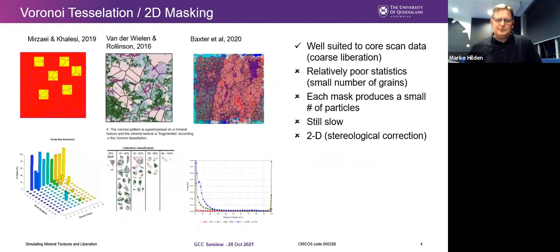Another popular modeling method is to use 2D images of the intact texture and to overlay a tessellation or fragmentation mask, which defines the particles. So simple shapes like circles or squares have been used, but a lot of the recent work uses Voronoi tessellations. An advantage of this approach is it has the potential to be extended to non-random breakage as well. Also, the method is well suited to core scan data and studying coarse liberation. But again, each tessellation makes only a relatively small number of particles. And if you have to repeatedly make particles to get good enough statistics, it's still fairly slow. And it is a 2D approach. But it does have its place as well.